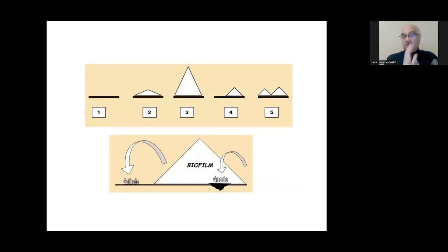To summarize, you have these 5 steps. In number 1, you have a bare metal surface. In number 2, biofilm starts to be formed. Number 3, biofilm starts to grow in thickness. Then a part of it could be removed. Number 4, but the rest of the biofilm that remains could start to increase its metabolism with a very low level of food, and regrowth happens in number 5. And therefore, you see that the anode, or better to say pitting at the anode, can be formed here, and how this biofilm could look. Are there any questions?